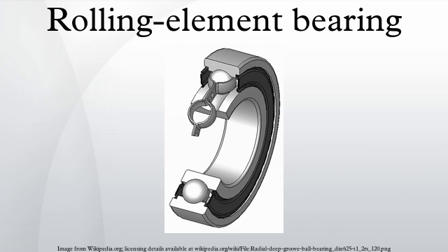Pressure-induced welding can occur when two metal pieces are pressed together at very high pressure and they become one. Although balls, rollers and races may look smooth, they are microscopically rough. Thus, there are high-pressure spots which push away the bearing lubricant. Sometimes the resulting metal-to-metal contact welds a microscopic part of the ball or roller to the race. As the bearing continues to rotate, the weld is then torn apart, but it may leave race welded to bearing or bearing welded to race.